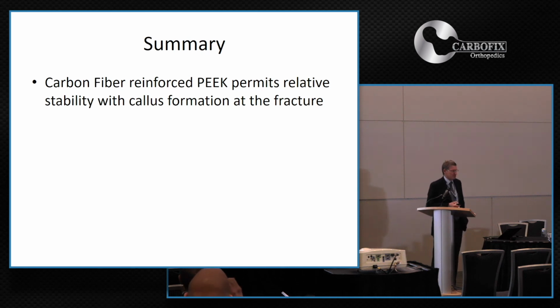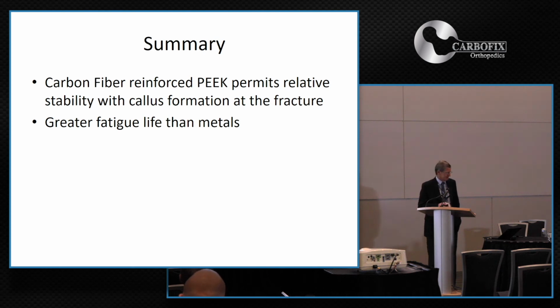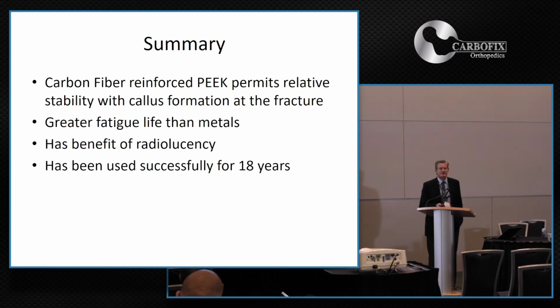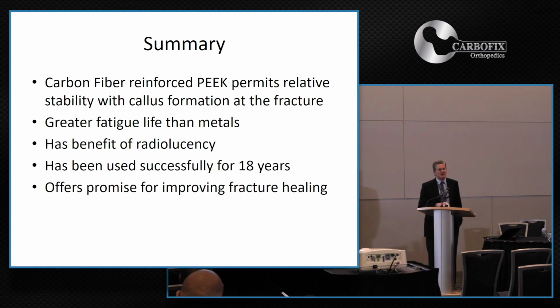So in summary, carbon fiber reinforced PEEK permits relative stability with callus formation at the fracture site, has greater fatigue life than metal implants, has the benefit of radiolucency, which can help both intraoperatively and postoperatively in terms of your assessment of the fracture healing and reduction. It's been successfully used by our spine colleagues for 18 years and may actually offer improvements in terms of our care of patients and maybe a paradigm shift in terms of how we go about fixing fractures.